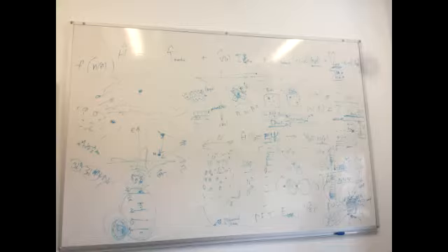If you want to dope your system, you can move this Fermi level somewhere here. Especially these are transition metals, so they're kind of semi-filled. The Fermi level is exactly in the middle of this band of states. Because of that, half of them are empty, half of them are filled, and all kinds of magnetic effects start to appear. Because there are a bunch of states close together, you can polarize all electrons with a spin up, or all down, or you can make up, down, magnetic, non-magnetic configurations.